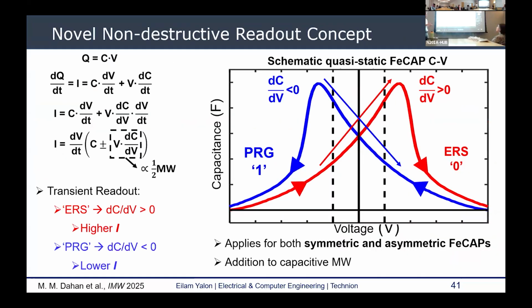So building on a similar concept, what we proposed goes back to this butterfly curve of the capacitance versus voltage of a ferroelectric capacitor, which has different behavior of the capacitance in the different polarization states. So you would see that at zero bias, this is an ideally symmetric capacitor, and at zero bias, there's no difference in the capacitance, but the derivative, or the change of capacitance with voltage, has an opposite sign. And we can probe that different sign if we just look at the transient current when you apply a small transient voltage.